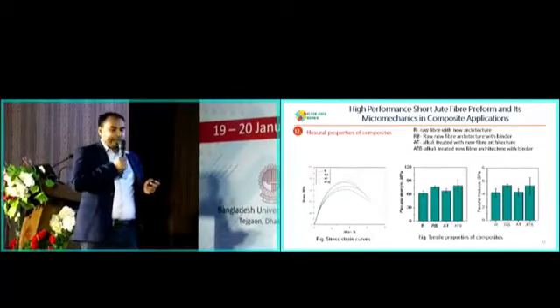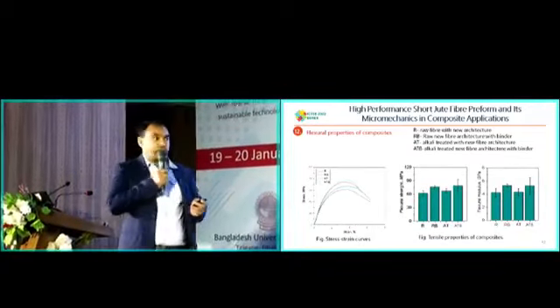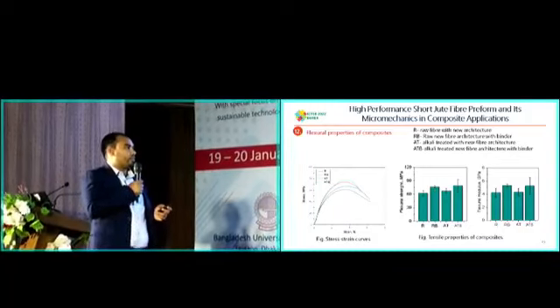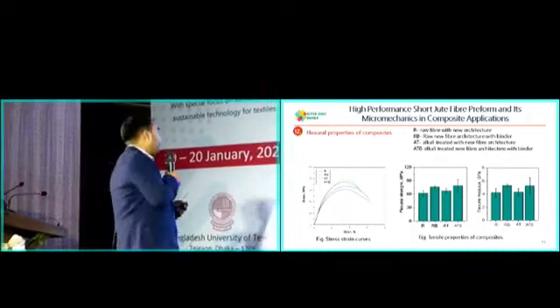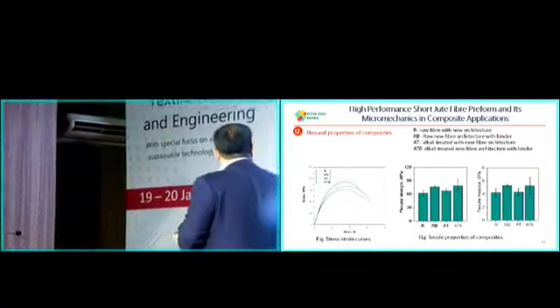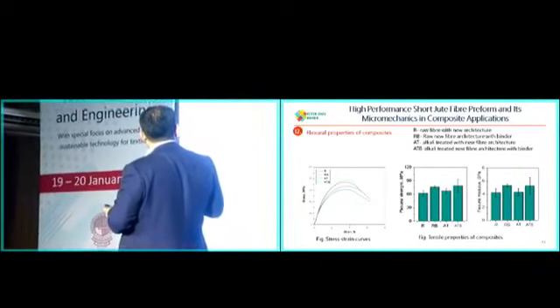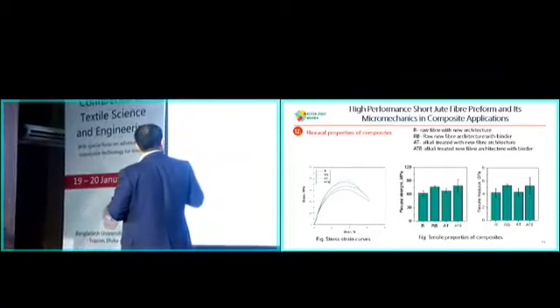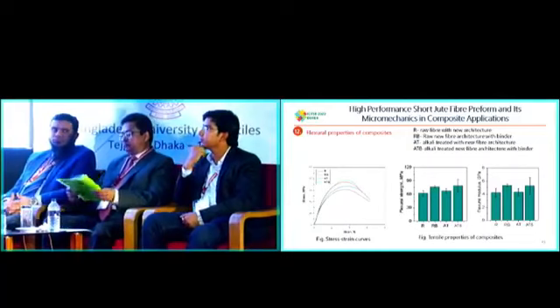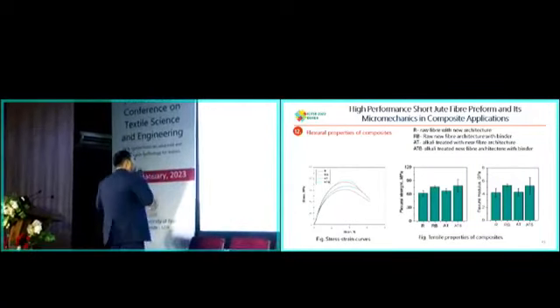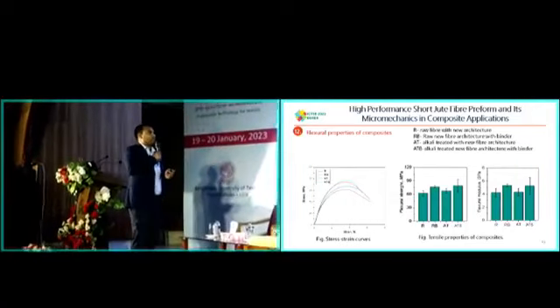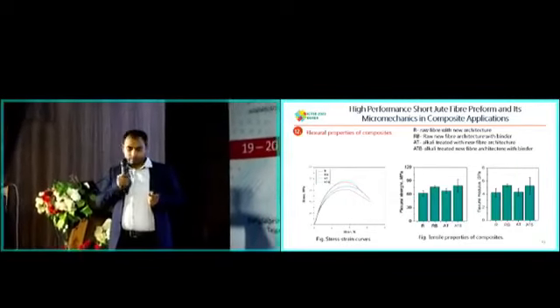Similarly, for the bending or flexural properties, you can see the flexural strength and flexural modulus have been compared in the figure. In the stress strain curve, the untreated fibers don't give that much in properties. When treated with different conditions, the strength has increased from 60 to nearly 88 MPa for flexural strength, and the stiffness increased from 4 to nearly 5.2.